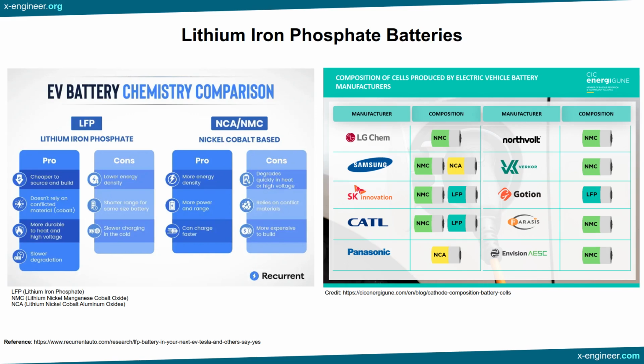More resistant to aging from fast charging. Although our preliminary Tesla results indicated that occasional fast charging does not have any drastic, short-term effect on range, laboratory science has shown us that NCA and NMC batteries are sensitive to long-term degradation from frequent high-voltage, high-heat charging. The same is not necessarily true of LFP batteries. This is because LFP batteries rely on a 3D, crystalline structure, and can withstand high temperatures without decomposing.